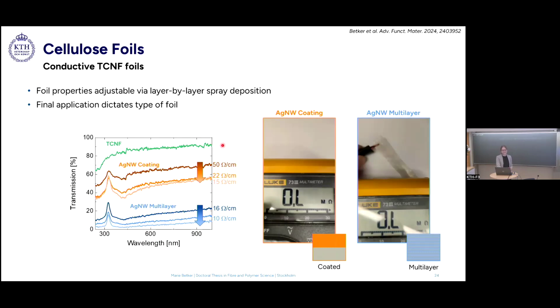Here you can see the transmission in the optical range. In green here, we have again the TEMPO cellulose, only TEMPO cellulose. It's not conductive, but highly transparent. Then we see the coated foil, and there's also a video here. This is an example of such a coated foil, coated with the silver nanowires. You can see it's transparent, and you can also see it's conductive. What we see here is the resistance, not the conductivity, so low resistance means high conductivity. But you can also see that this foil is a bit prone to mechanical deformation, so the values are not so stable here.